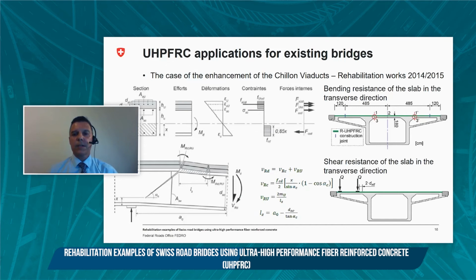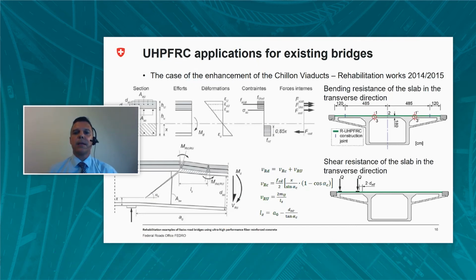The length of this zone is estimated from the mouth of the inclined crack to the position of the concentrated load. It thus depends on the angle of the inclined shear crack and on the length of the shear span. For the present slabs, the shear span corresponds to the distance between the side of the concentrated wheel load and the web of the box girder. It is equal to twice the effective flexural depth of the composite section, as shown here for the cantilever slab.